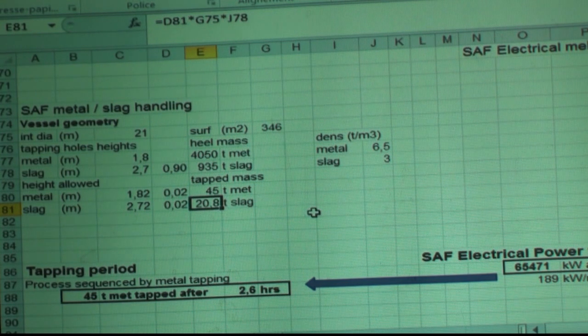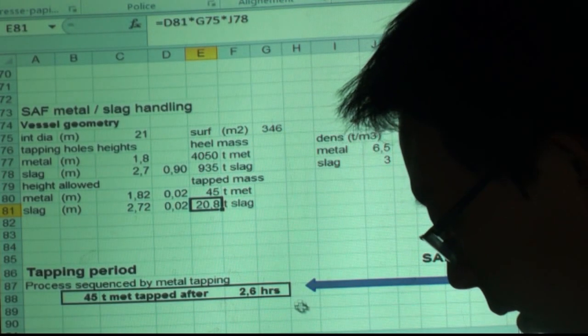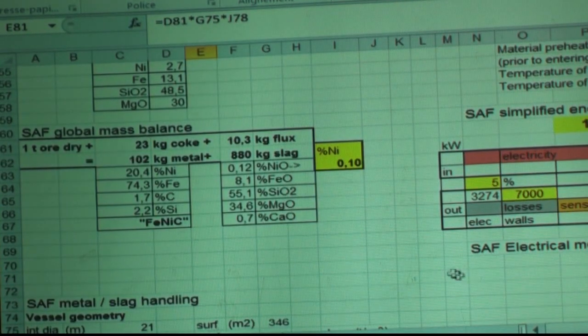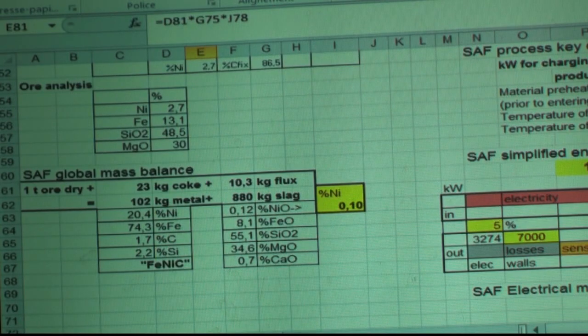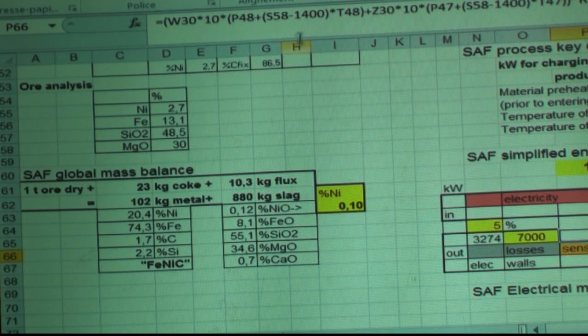Look, there is one explanation already, and this is very important. The metal is tapped at 1500, and the slag at 1600. And that's high temperature. I had to change the formula, because here you have sensible heat, you have the metal, and you have the slags.